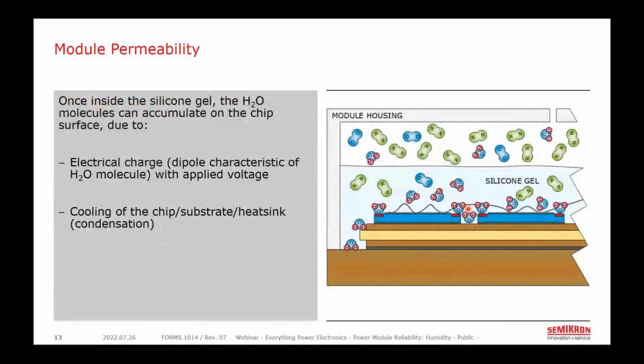So once inside the silicone gel, the water molecules do two main things. The water molecule is a dipole, meaning that the side of the molecule with the oxygen atom has a partial negative charge. This charge causes the molecules to be attracted to the electrically charged surface of the chip and the substrate where they can accumulate. The other method of moisture accumulation is not electrical but thermal. So if the chip or the surrounding surfaces are cooled below the dew point for the given conditions, outright condensation can occur. We'll look at how this can occur later in the presentation.